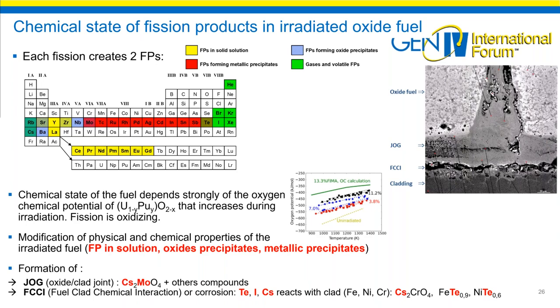We have a modification of physical and chemical properties of the irradiated fuels due to these fission products in solutions or under different oxides precipitates or even under metallic precipitates. We have also, because of the fission products diffusion, the formation of the jog. The jog is joined between the oxide and the cladding. You can see here on the ceramography on the figure in the left. This is mainly compound with the molybdate of cesium plus other compounds.